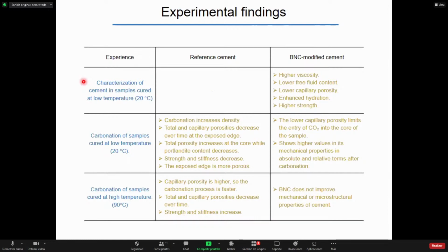In the characterization of cement samples cured at low temperature, we saw that the addition of bacterial nanocellulose increases viscosity, reduces the free fluid content, which reduces the capillary porosity, enhances hydration, and increases cement strength.